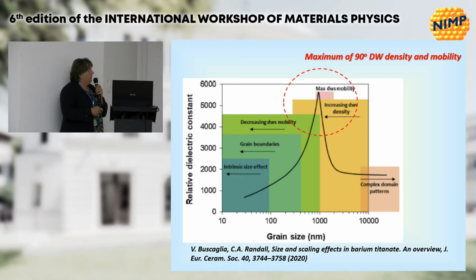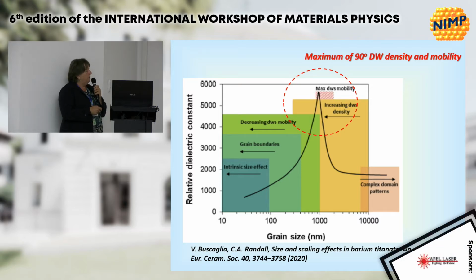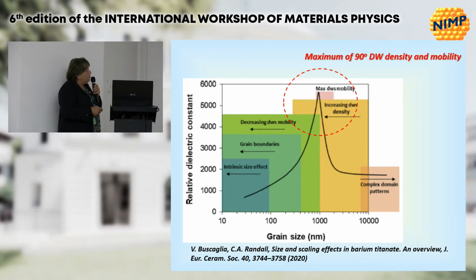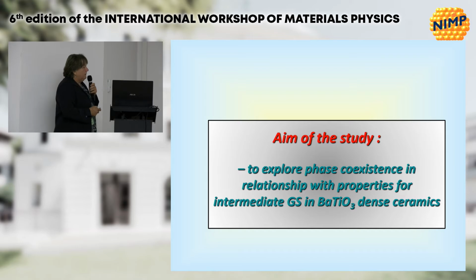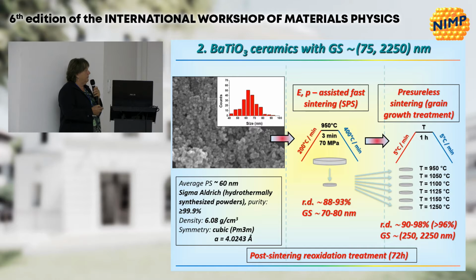Here is a maximum of both domain wall mobility, which was really probed by the group from North Carolina State University, but it is also claimed to be a maximum of domain wall density. Practically, there are some nanoscale studies showing that here the number of domain walls is increased, but there is not a study along all this range of sizes. Well, we wanted to study if the phase coexistence has some role or is modifying the grain size effects that were quite well known in typical tetragonal barium titanate, and to see if this interpretation related to domain walls is valid, or is observed also in this case.